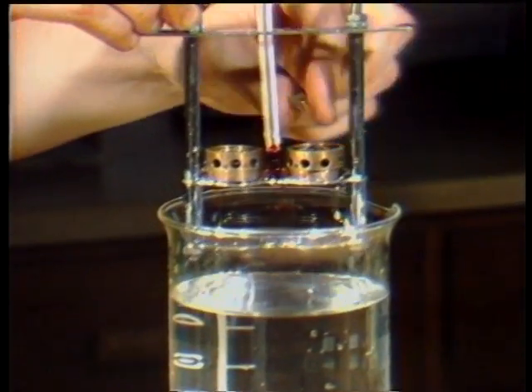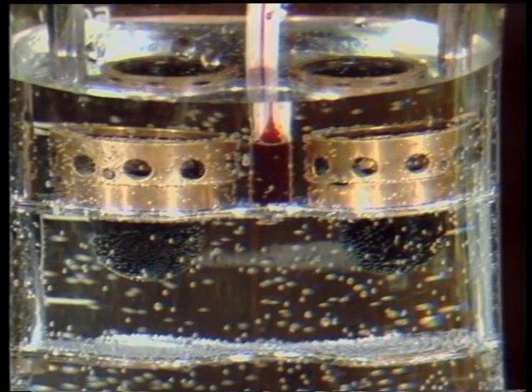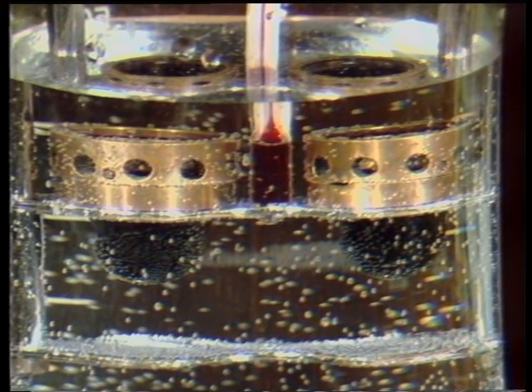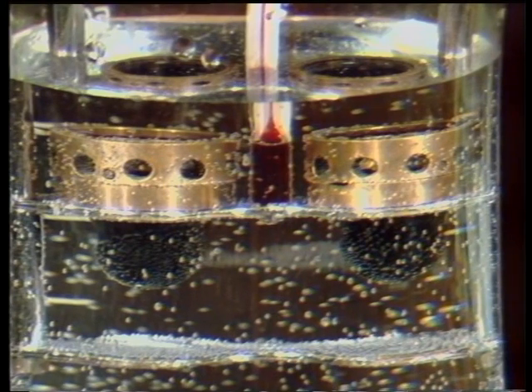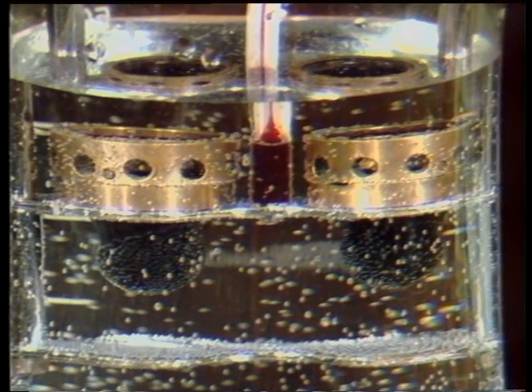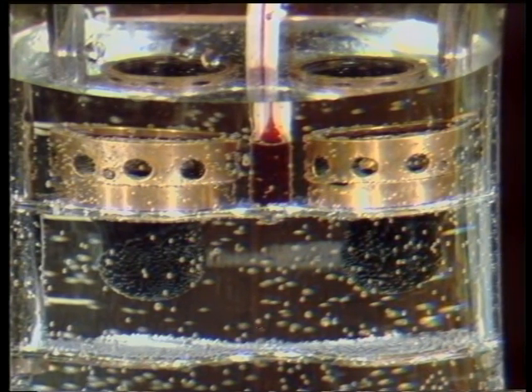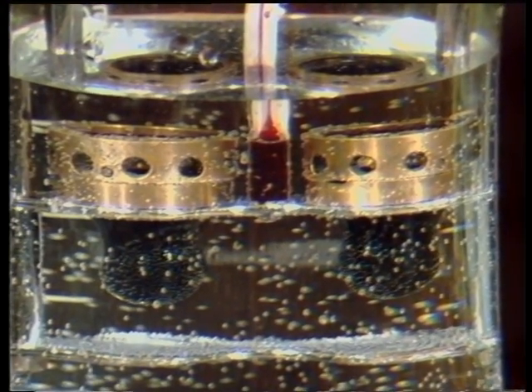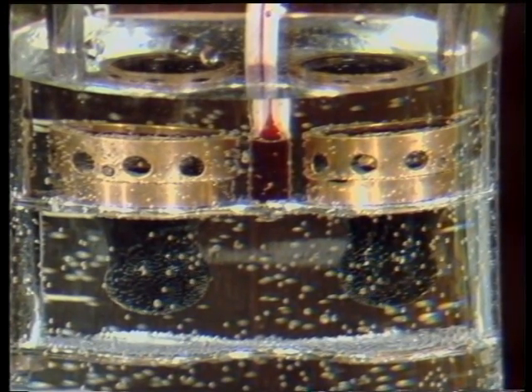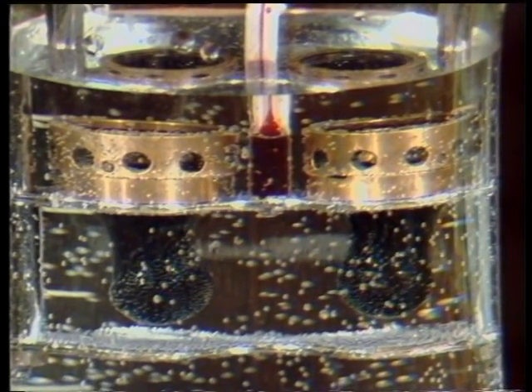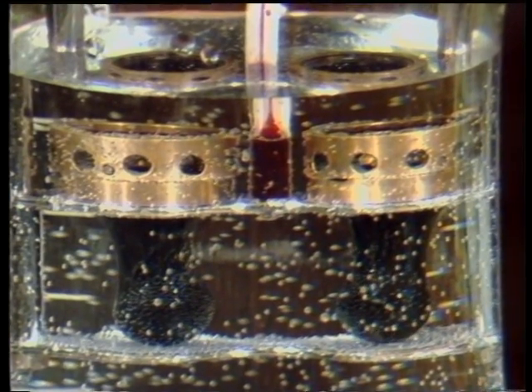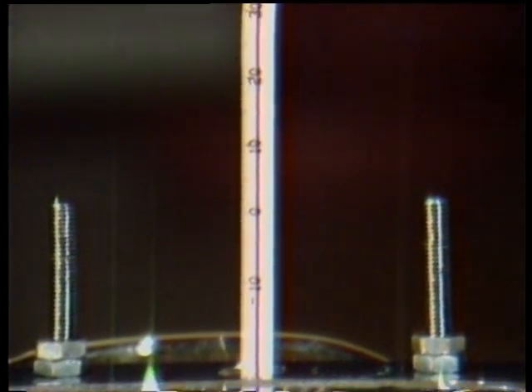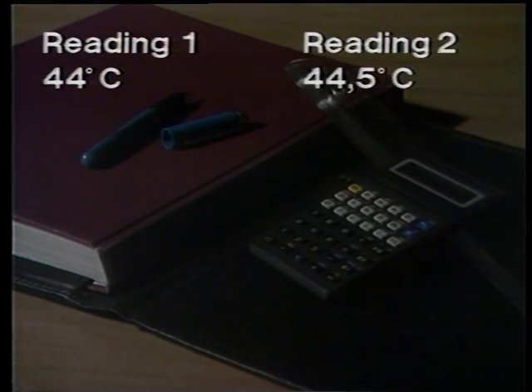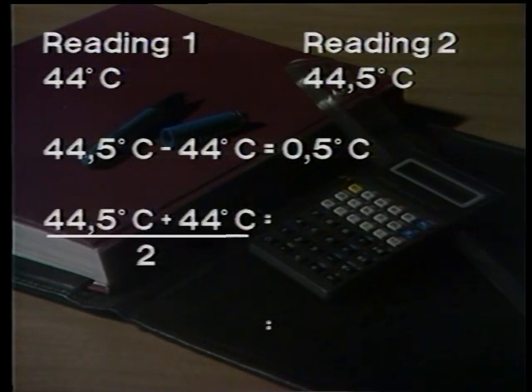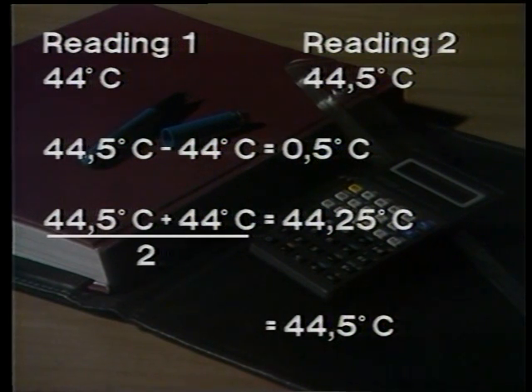Place a steel ball on each of the test specimens. Heat the water so that the temperature rises at 4.5 to 5.5 degrees Celsius per minute. There are practical difficulties in obtaining the specified rate immediately after the heat is applied to the water. However, if after 3 minutes the rate of temperature rise does not fall within the specified limits, repeat the test. Read off the temperature shown by the thermometer to the nearest 0.5 degree Celsius at the instant that the bitumen surrounding the ball touches the base plate. If the difference between the readings exceeds 1 degree Celsius, repeat the test. Calculate the mean of the 2 recorded softening points rounded off to the nearest 0.5 degree Celsius.